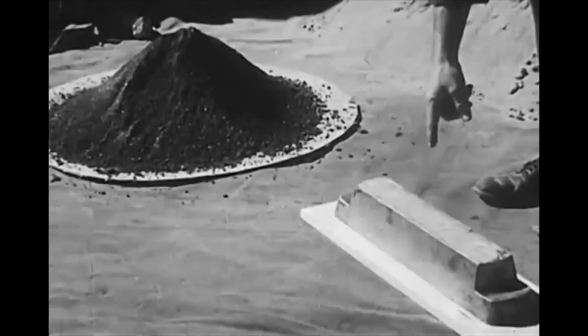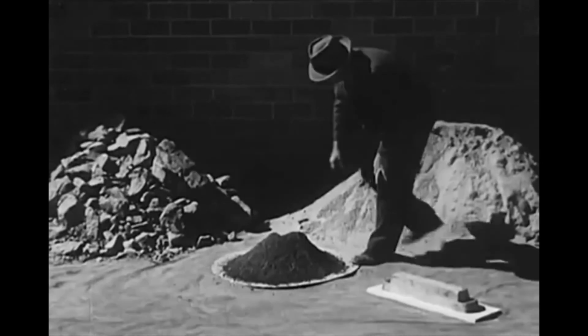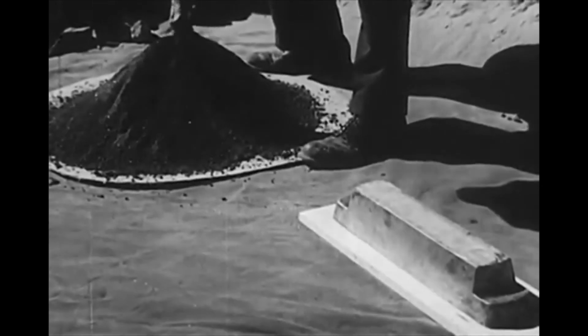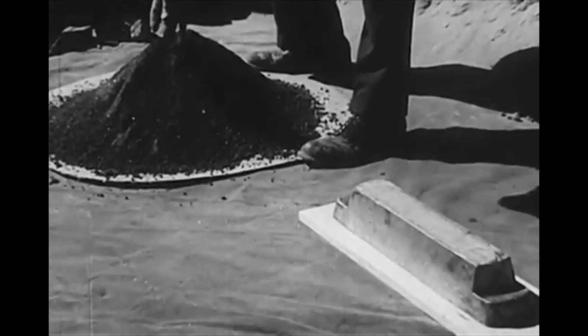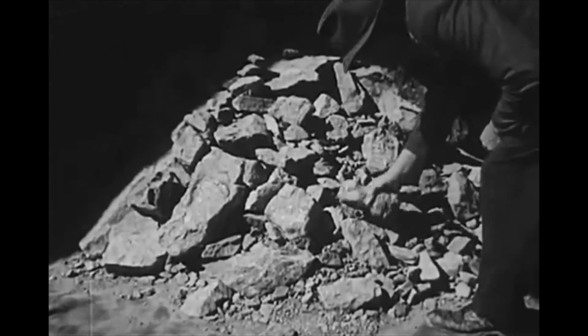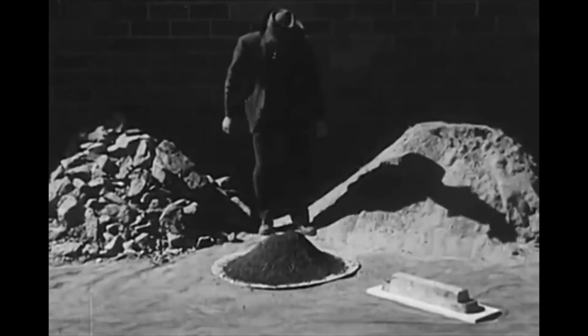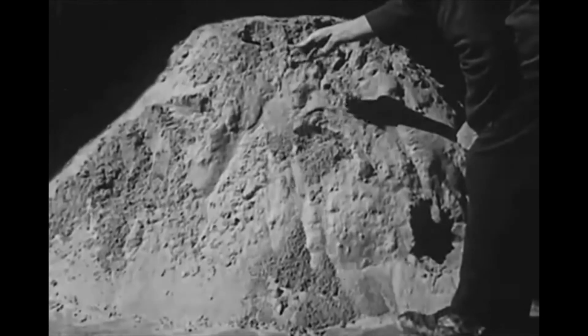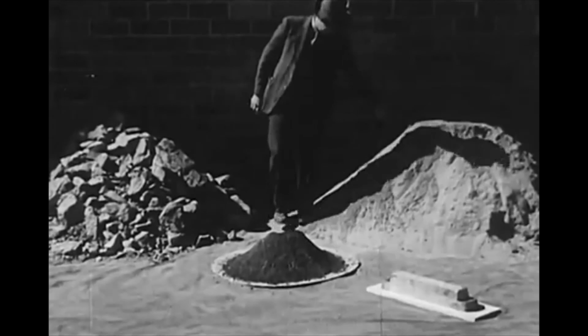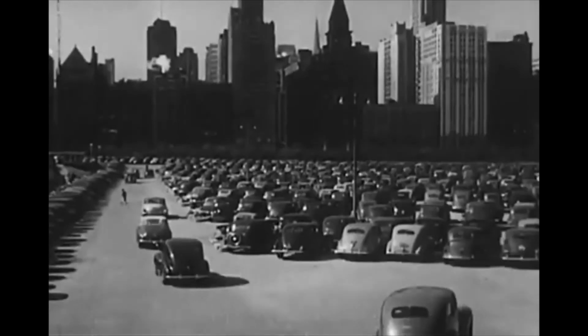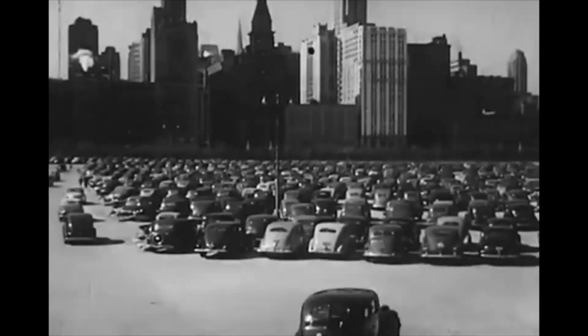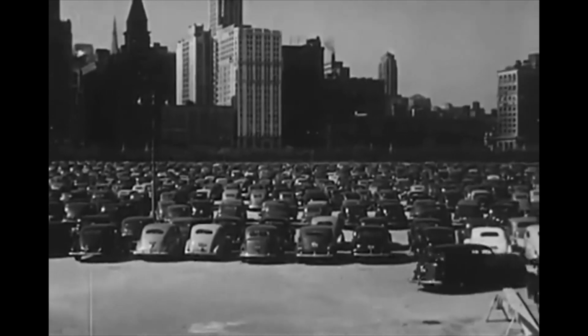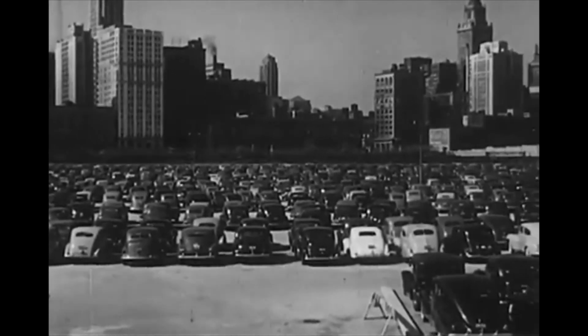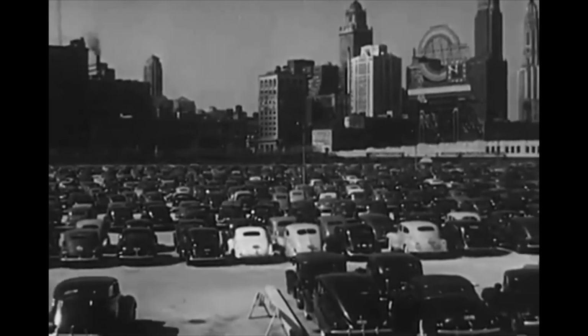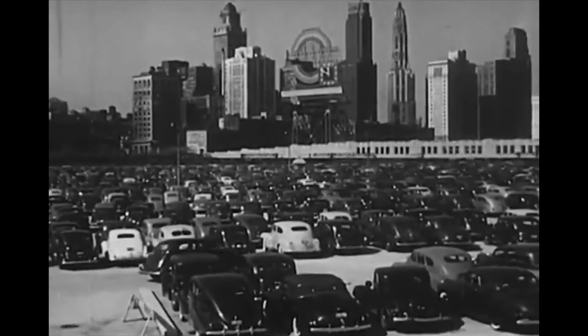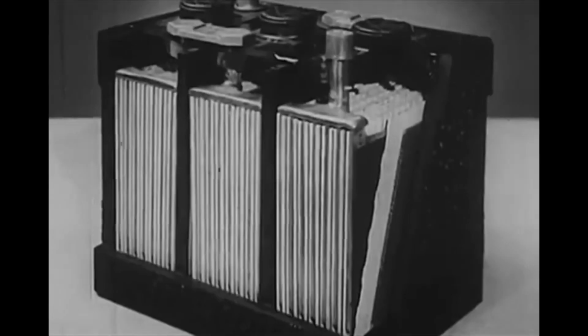This pig of lead, weighing 100 pounds, has been obtained from the smelting of about 138 pounds of concentrates, which by milling have been produced from approximately 3,300 pounds of ore taken from the mines. In the milling process, about 3,100 pounds of almost lead-free limestone was discarded as waste, locally called chat. The industry consuming the largest tonnage of American lead is the automotive industry. Almost every car uses lead in storage batteries, solder and bearing metals, and even in brake linings. In addition, lead is used in gasoline for better performance.